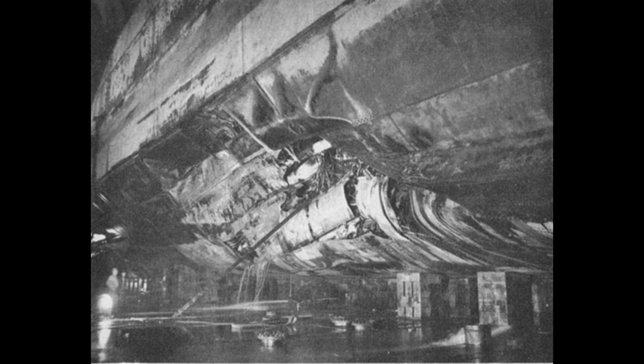Out of 173 LSTs that participated in D-Day operations, 14 sustained damage severe enough to require shipyard repairs after the battle. 3 were total losses, abandoned on the beach after sustaining direct hits that killed their crews and started uncontrollable fires. But not one single LST broke apart structurally. Not one suffered catastrophic weld failure that turned the vessel into 2 pieces of scrap metal.